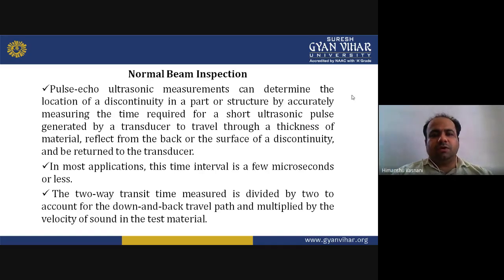So what is it doing? It is helping to determine the location of the defect in the part. How? By accurately measuring the time required for a short ultrasonic pulse generated by the transducer to travel through a thickness of material, reflect from the back or the surface of a discontinuity or a defect, and be returned to the transducer.